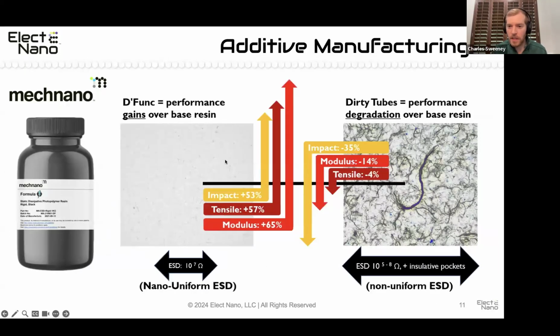This is an example of the dispersion technology that MechNano uses. These are high resolution images of the nanotube dispersion. If you just take off-the-shelf nanotube powder and try to mix and stir it into SLA resins, you get the image on the right here, with lots of ropes and bundles and clumps. The key to our technology is the ability to disperse and evenly distribute, and eliminate the clumps and chunks of carbon nanotubes in these SLA resins.